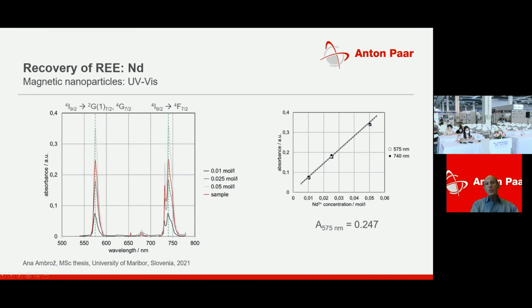In the adsorption experiment, we exposed a solution of 0.05 mole per liter of neodymium to a sufficiently high amount of magnetic nanoparticles for a specific time. After removing the nanoparticles with an external magnet, we obtain a remaining concentration of 0.035 mole per liter, which corresponds to a removal of neodymium ions by about 30%.